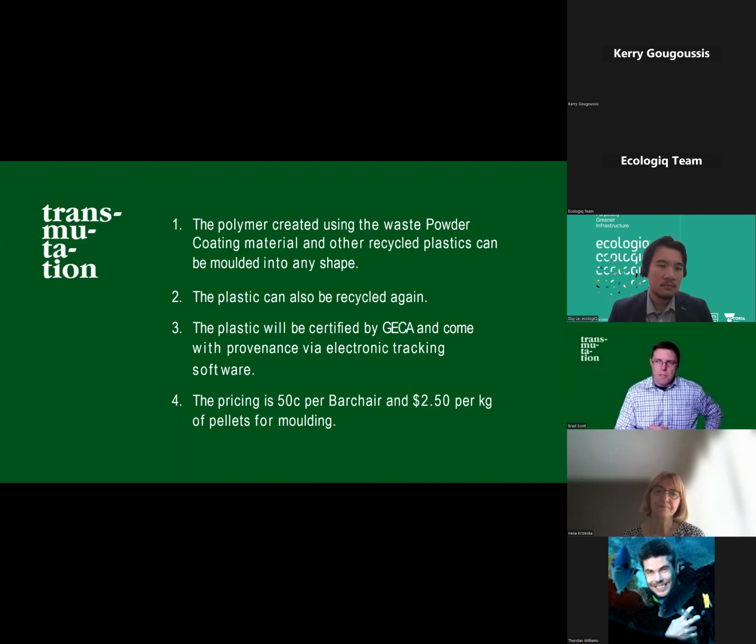We're pelletizing it so that it can fit into the traditional injection molding industry. So basically we can present a standard pellet to an injection molder and they can mold it, and we give the specifications for temperature and pressure for the machinery to operate at. We'll also look at whatever's being molded, that current design, and make sure that our plastic meets the specification before we put it into the mold, because the mold's the most expensive part of that process. So if it can go into a current shape, no problems, but we'll test that on the computer programming before you start producing a whole heap.